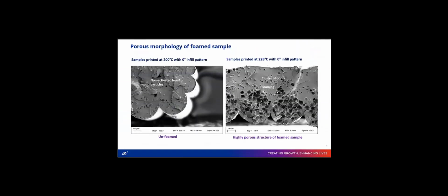So these are cross-section images of the samples printed at 200 and 228. It is very evident that the extrusion temperature affects the microstructural morphology. And you can see the porous cluster of pores because of the foaming. You can see the foamed structure for the foamed samples, which shows that the extrusion temperature affects the microstructure of the polymer.